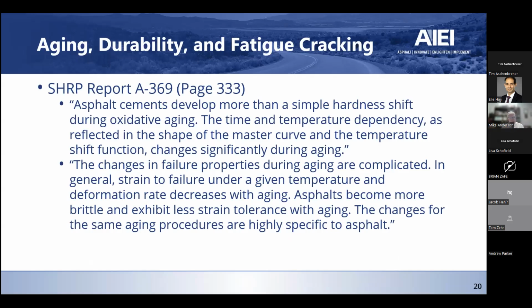They further talked about you seeing something more than just a simple hardness shift that occurs during oxidative aging. It changes time-temperature dependency as well, and that's reflected in the shape of the master curve and how that changes. And it further notes that the changes that occur are complicated. In general, strain to failure and deformation rate decrease with aging. The asphalt becomes more brittle and exhibits less strain tolerance with aging. So that's all out of the SHRP report.